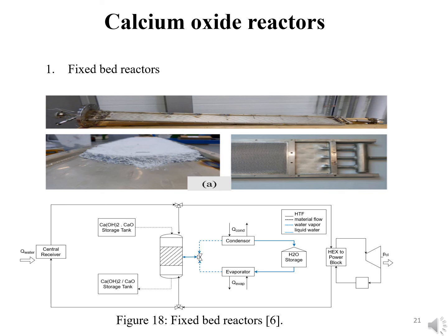Researchers claim that the reaction rate is the most influential parameter for the reactor's efficiency. The experimental findings show that the greater the charging temperature during the charging stage, the faster the heat storage rate will be. A new indirect reactor was designed, and experimental demonstration of hydration dehydration under low vapor pressure was explored. The results suggest that it is possible to run the storage system at low vapor pressure.